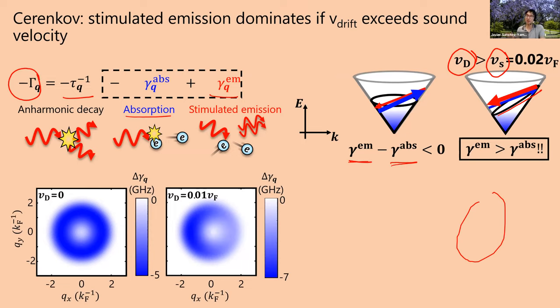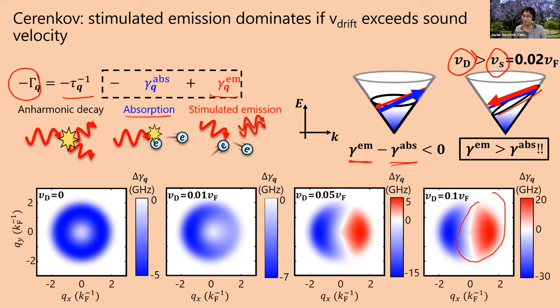And that's pretty important because you can have this stimulated emission process. That means that if you emit a little bit, those phonons can then cause the emission of more phonons, which can then cause the emission of more phonons, and your phonon population can grow and grow and grow. And this is the process of Cherenkov amplification of phonons.